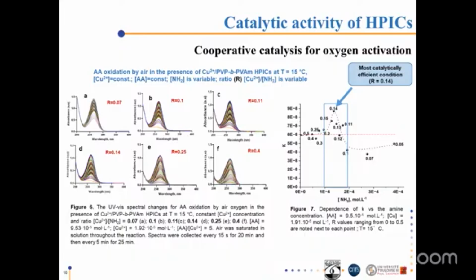The presence of an excess of polymer at ratio less than 0.12 leads to complete copper complexation, but prevents the formation of colloidal complexes. In these conditions, the resulting rate constant values are lower than those of free copper sulfate.